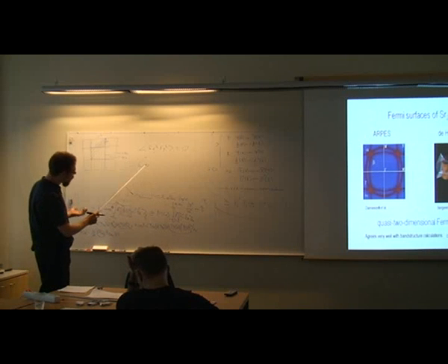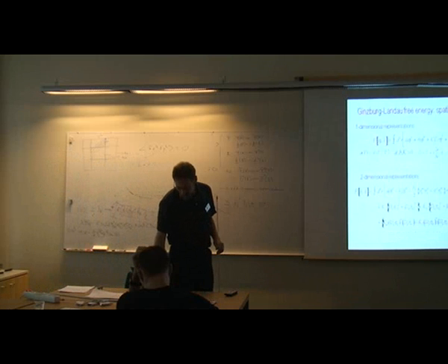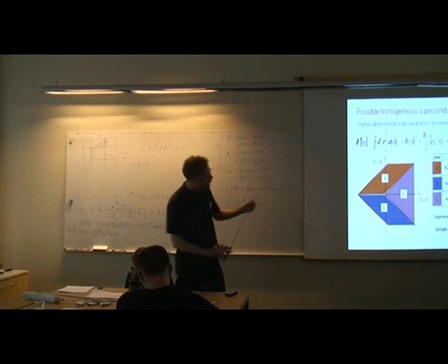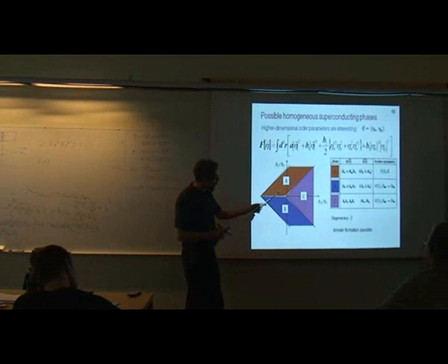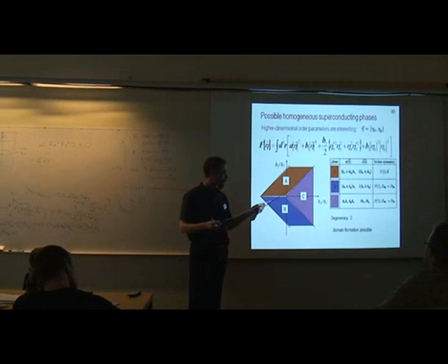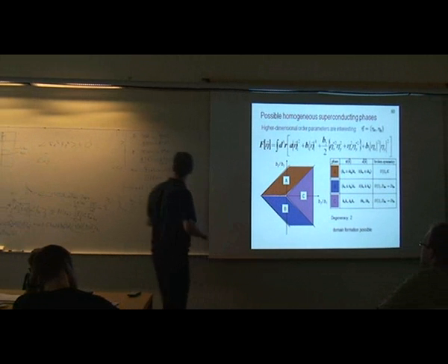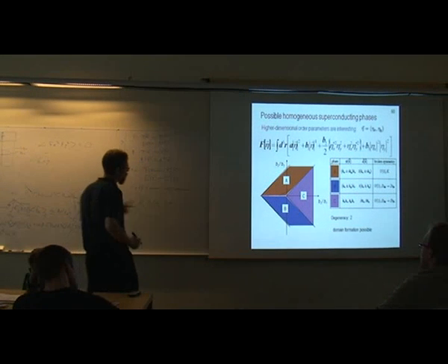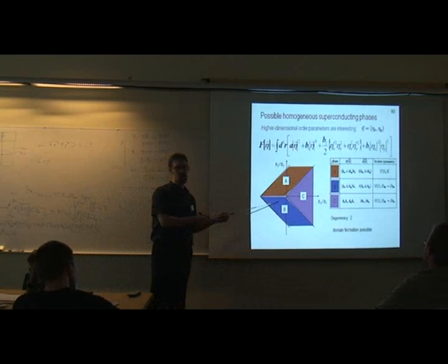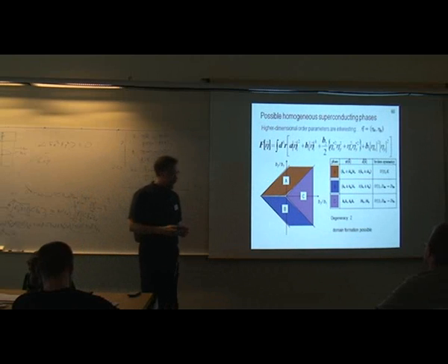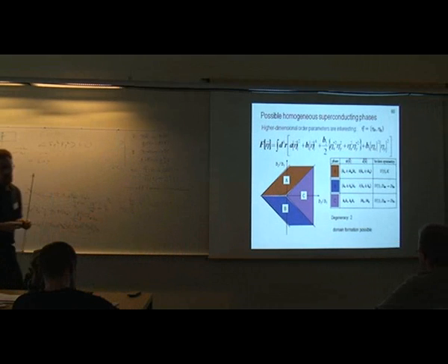And I won't go through the details, but now, if you add to your Ginzburg-Landau free energy functional a strain energy and a coupling between the strain and the order parameter, then, not surprisingly, you can find that you can tip the balance if you're in this region to go into this phase. And so coupling between some nematic order parameter in strontium ruthenate, as long as it drives a strain in this direction, will push you down into this phase in principle. So you could get a line node phase if you're lying close to those boundaries.